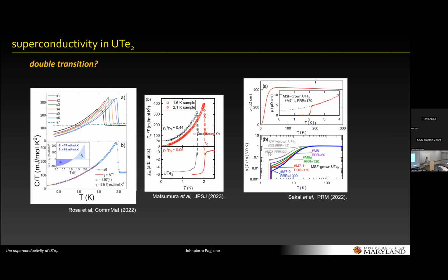And then here's the data about residual resistivity that I think someone asked about. So going from non-superconducting all the way down to the highest RRRs, you approach roughly 1,000. Between 500 and 1,000, it depends on how you define it. But so from on the order of 1 to 2 to the order of 1,000. That's the range. That's the molten salt flux. Yes. I won't say how, but you don't need molten salt. We can grow crystals without molten salt. We get the same. I get the same RRR.